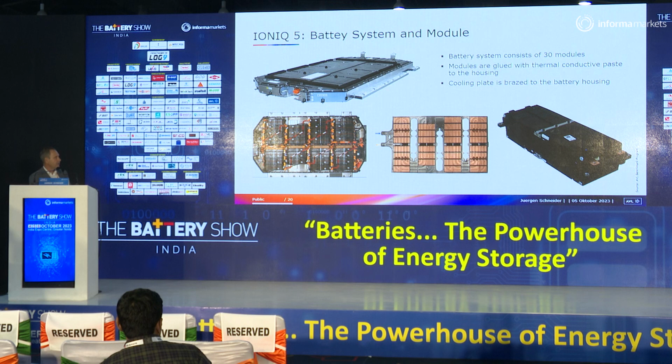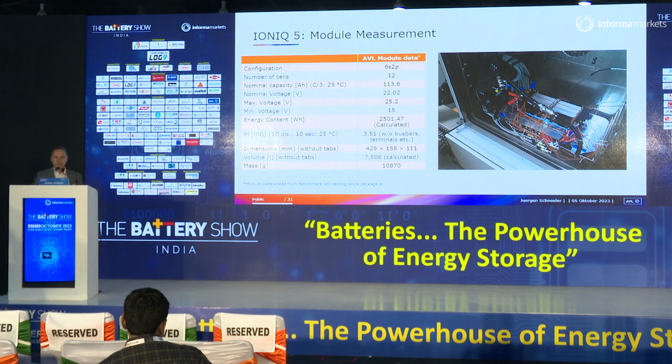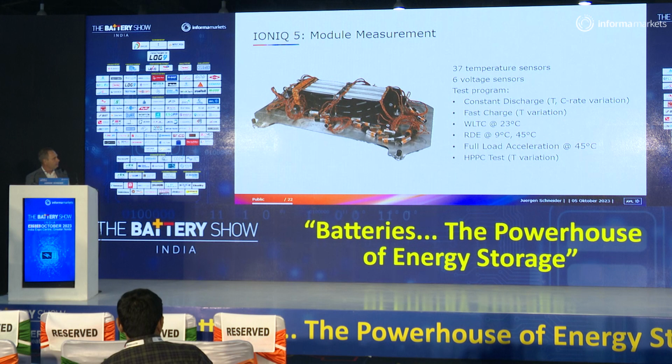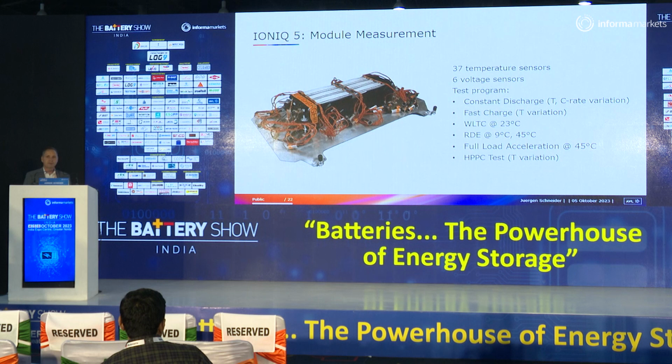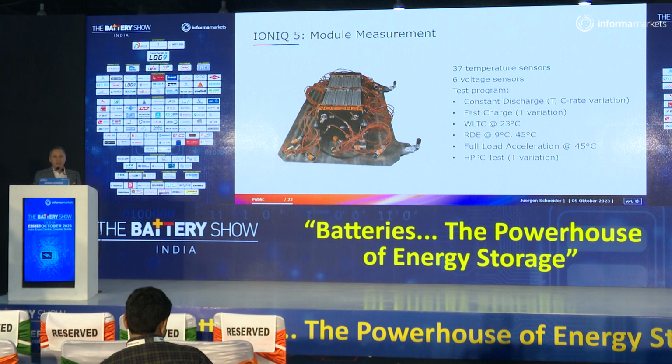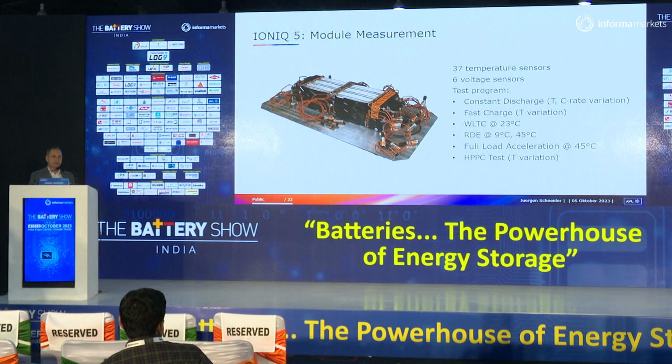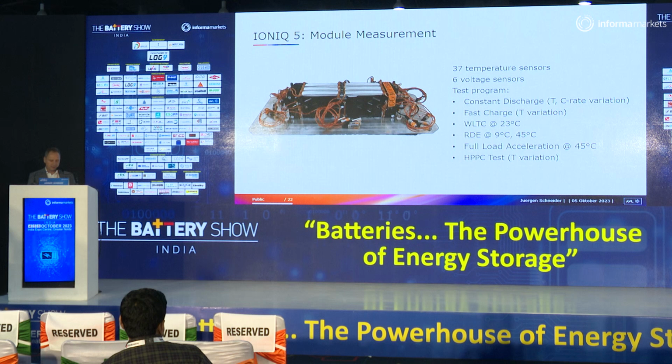Not only the battery pack, but also the module. This was important for us to understand how accurate we can be with our simulations when we later put it on a test bed. So this is our battery module after we put in some cables with 37 temperature sensors and some voltage sensors, and did a huge list of challenging tests with different C rates, different temperatures, driving profiles, charging profiles, and HPPC tests, to see how those compare to our simulation model.